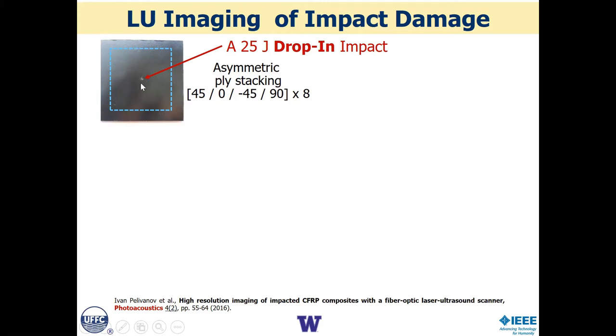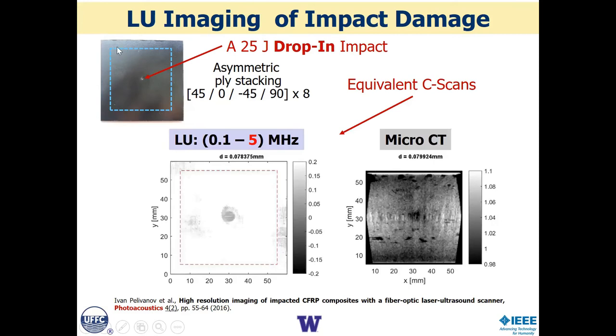We then scan this area, shown in the blue here, in a few minutes with our rapid laser ultrasound scanner. We then took the material, sectioned it, brought it to the medical center, and did high resolution micro CT on this section, which took many hours and cost a few thousand dollars because we had to rent the facility to do this. We re-rendered the images so they're in the same format as the C scans, and then compared the state of the art in destructive testing of these materials to this very cheap, rapid, compact laser ultrasound system.